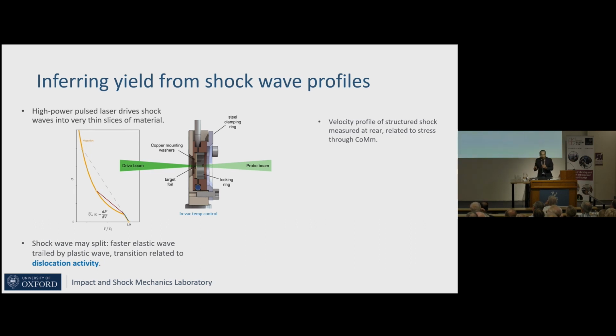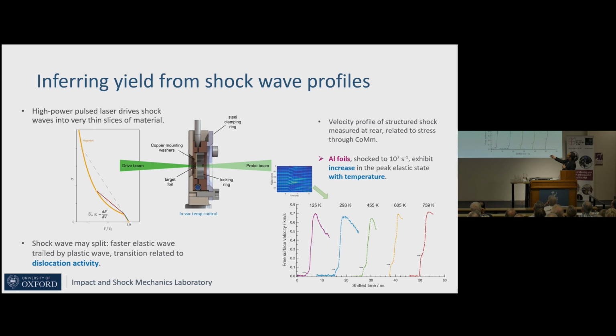So it's analogous to what we would do in a lab when we're doing quasi-static loading, where we're looking for the yield point. So we're just looking for a dynamic yield point. And we could also then, with a probe beam, measure on the rear surface and say, okay, well, then what should pop out should be an imprint of elastic behavior followed by plastic behavior. And as we have done before, we look for that folding over, or in this case, it's this kink in the curve, and that represents the yield stress of the material.